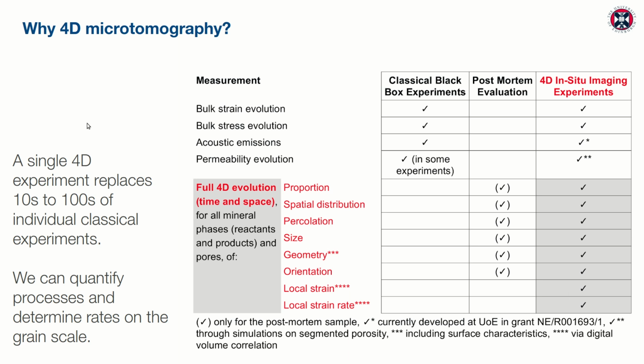Another 2 points to keep an eye on, and they are good justification for doing 4D microtomography, is really that a single 4D experiment actually replaces tens to hundreds of individual classical experiments, right? Because every single 3D scan constitutes one of these classical experiments. And the other important point is, rather than quantifying processes on the bulk scale, we can quantify processes and determine rates on the grain scale, and I think that is also quite important.